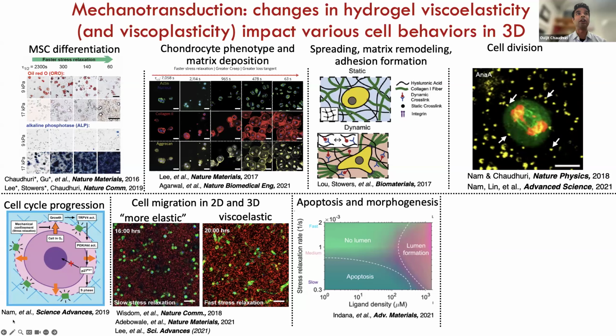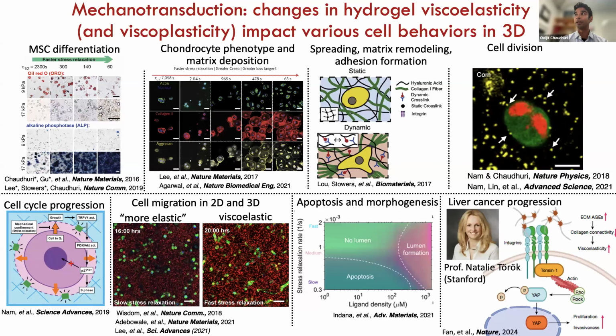Now, from the impact we see of viscoelasticity on cell division and cell migration, we might expect that changes in viscoelasticity could play a role in cancer progression, since cancer progression is intimately tied to proliferation and growth as well as invasion. And indeed, that's what we found. This is a study led by our collaborator, Natalie Török, who's here at Stanford. For patients with non-alcoholic steatohepatitis and type 2 diabetes, those tissues have the same stiffness relative to normal healthy liver, but enhanced viscoelasticity. And what Natalie and Jerome, the first author, found was that enhanced viscoelasticity activates malignant signaling and increased proliferation and invasiveness in those liver cells.